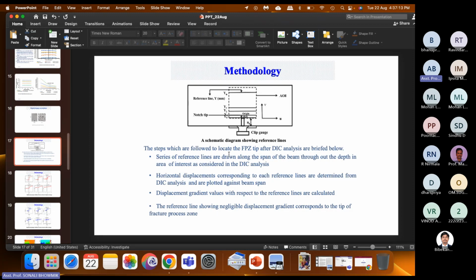This is a step-by-step procedure. It has been explained here, and using those data, each line's displacement has been found out, and it has been found that there is a change in displacement in each line. Also, definitely near the crack tip, the displacement jump will be more, but when we go in the upward direction, the jump will be less, because we have no crack opening here.